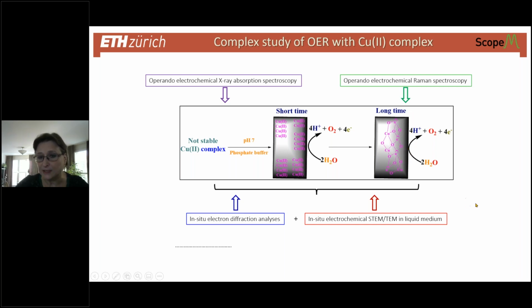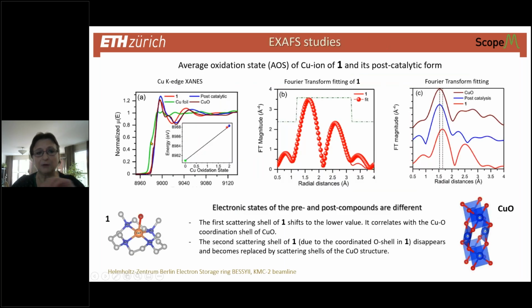This is our standpoint at that moment, and this is where in situ electrochemical liquid phase TEM made a difference. We confirm that it happens in two stages because operando electrochemical X-ray absorption spectroscopy and electrochemical Raman spectroscopy were applied at the different stages of the path, but TEM could follow the whole path. Now, phase analysis by TEM did state convincingly that we have a copper oxide phase forming, but to check the oxidation state and what exactly occurs, and what is the final state of the stable phase that becomes deposited on the electrode.